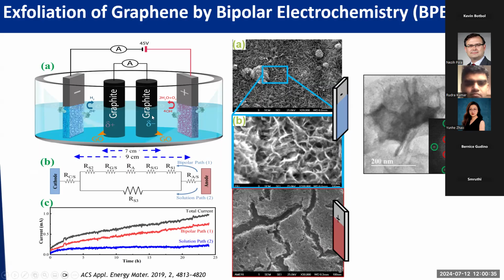Then once the graphene is exfoliated from the graphite, this feeding electrode, just like electrophoresis, will drive those graphene flakes in the solution. And this solution is DI water. You don't need any chemicals, not like electrochemical exfoliation or chemical exfoliation, where people use harsh chemicals. Here we just use DI water, and we can achieve graphite exfoliation into graphene. And at the negative feeding electrode, we even have reduced graphene oxide, compared to the graphene deposited on the positive feeding electrode. Those are mainly layer by layer